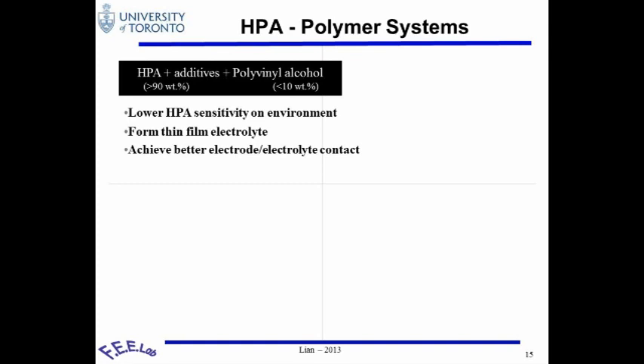We have a few generations of electrolytes, and our material composition primarily follows the rule that we don't have more than 10% non-conductive material. We try to use a very heavy load of conductor, more like a salt-in, polymer-in-salt kind of configuration.